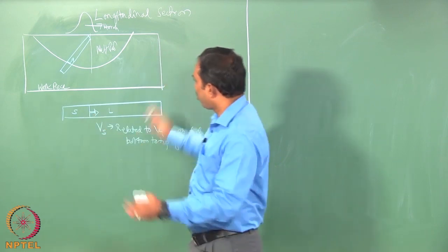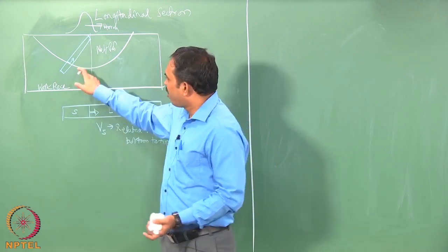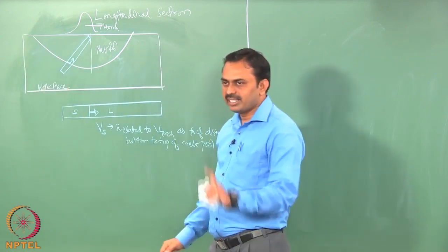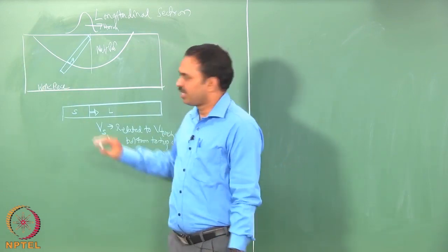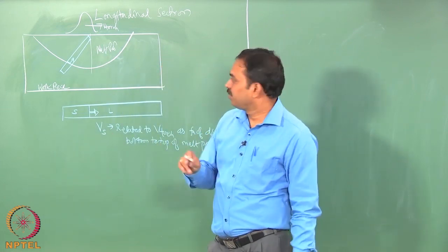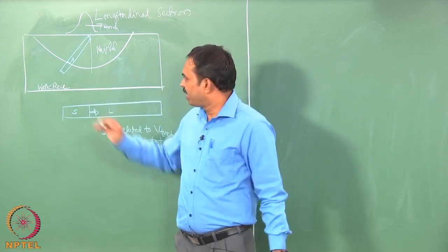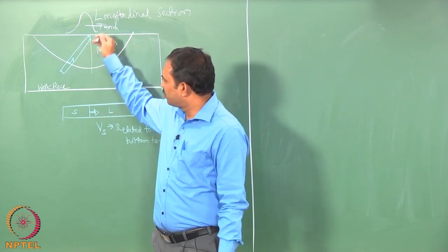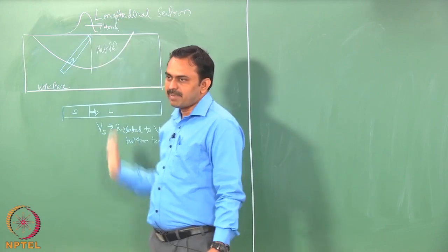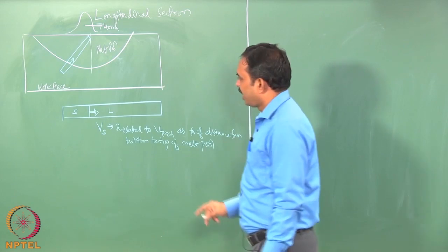And the domain is not the workpiece itself, but a small box that I have shown you here. This box can be replicated at every location on the back side to cover the entire solidified weld, and therefore, it is representative, and I have oriented the box in the direction of the maximum temperature gradient. The reason being that the solidification is always taking place anti-parallel to the maximum temperature gradient, and therefore, if the heat were to go this way, then the solidification is going in the anti-parallel direction. So, therefore, I have drawn the box along the maximum temperature gradient direction.